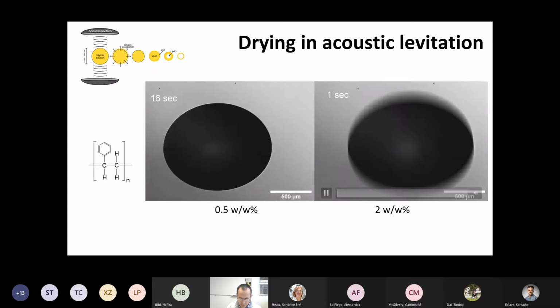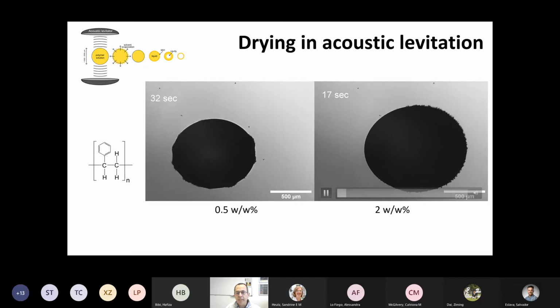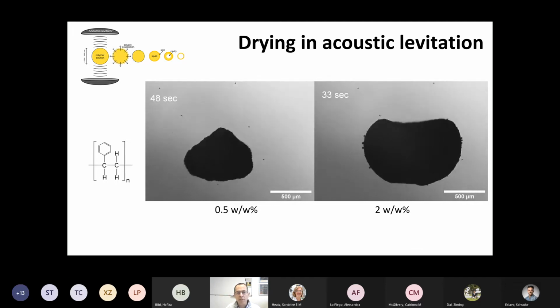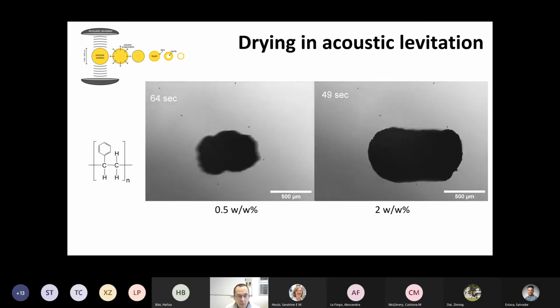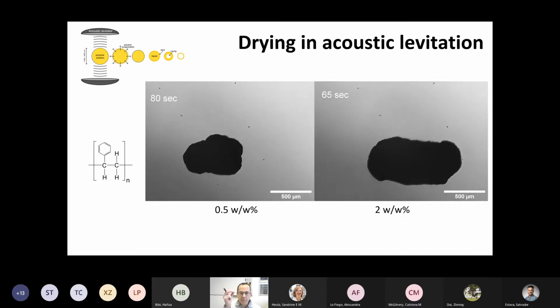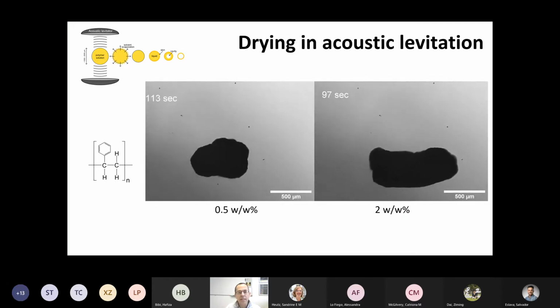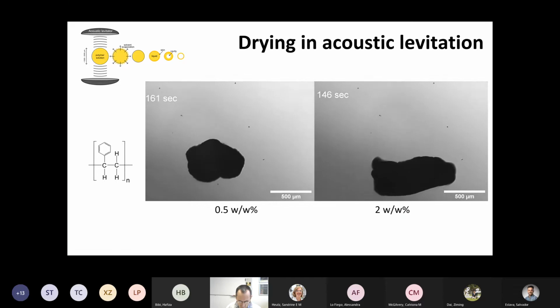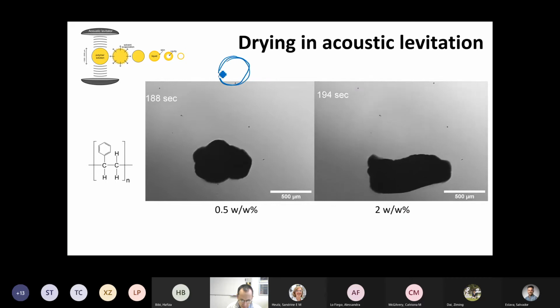I mean, under the effect of the acoustic field and the opposite gravitational field, you can definitely arrest the particles and image them around their center of mass. You can see that they oscillate around that node of the acoustic field. But you also might have noticed that they clearly undulate at the surface. So that was somewhere between the kind of circular profile to the sort of crumpled sheet profile.